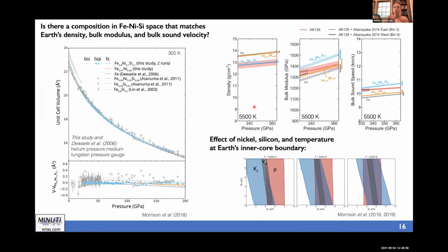And so to that effect, we did investigate the effects of nickel and the effects of silicon. And through work with determining the equation of state up to about 160, 170 gigapascals at GSECARS using a helium pressure medium and a tungsten pressure gauge, we were able to combine those thermoelastic properties when measured using NRIXS and the equation of state information and constraints to project these properties to the inner core conditions. And of course, what one sees markedly is the slopes for the bulk modulus and bulk sound velocity are significantly different. This is something that still needs to be understood.